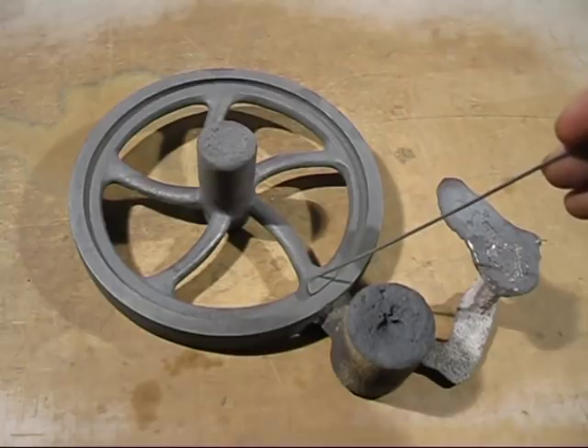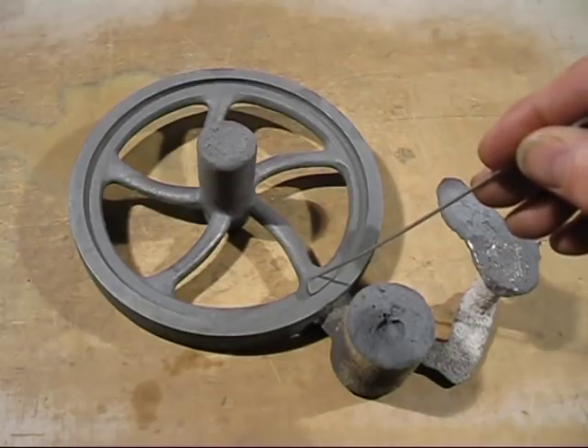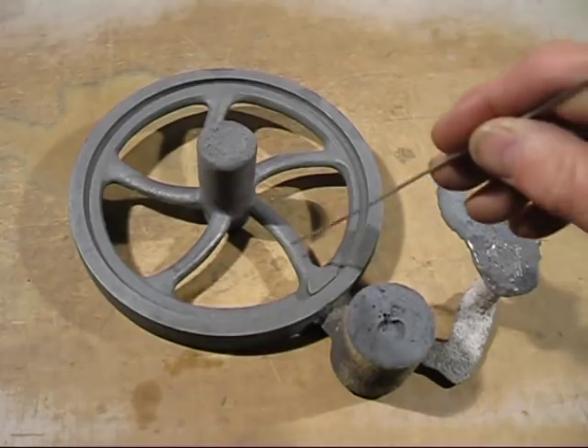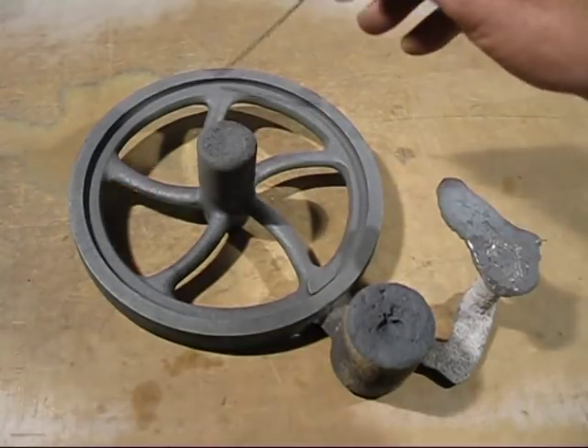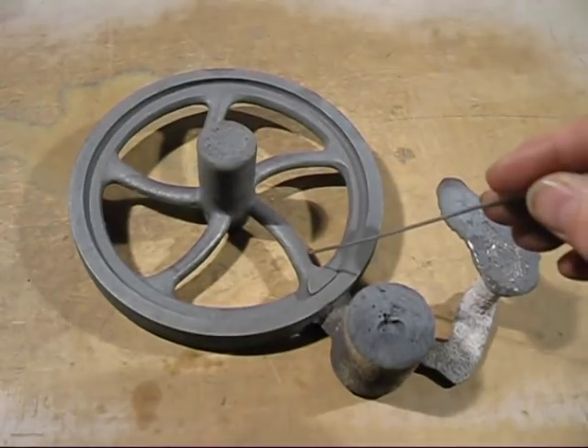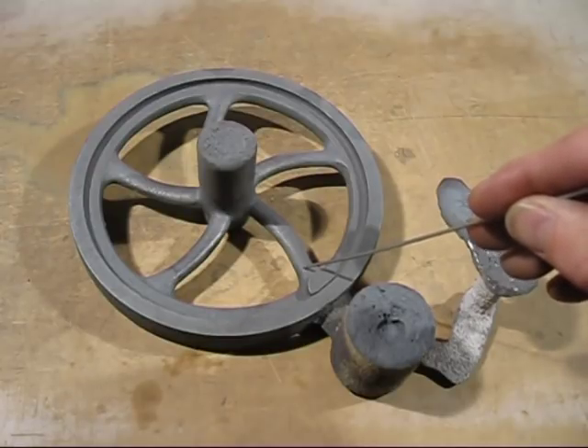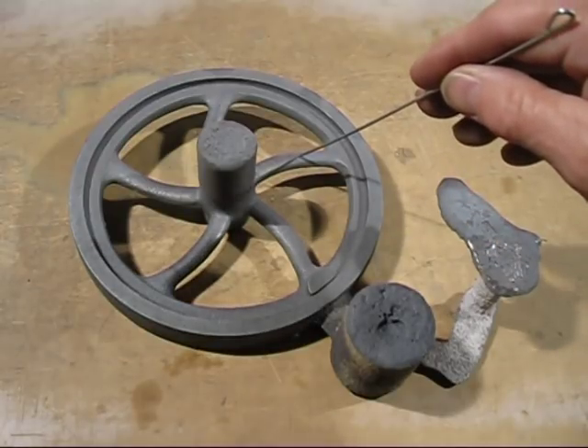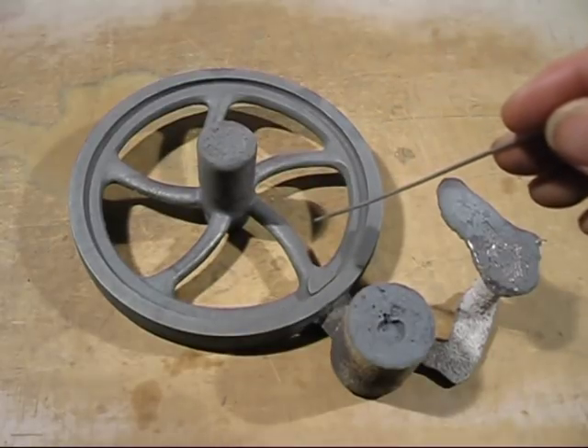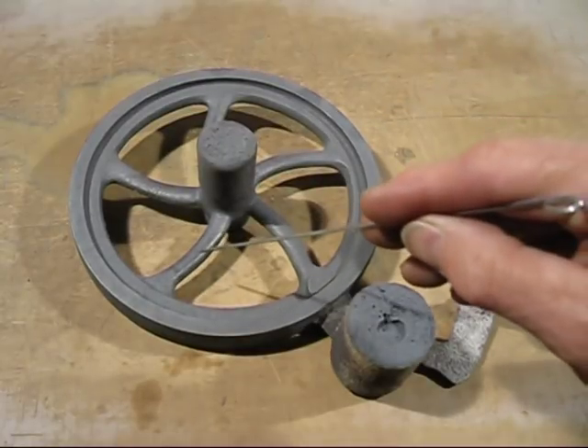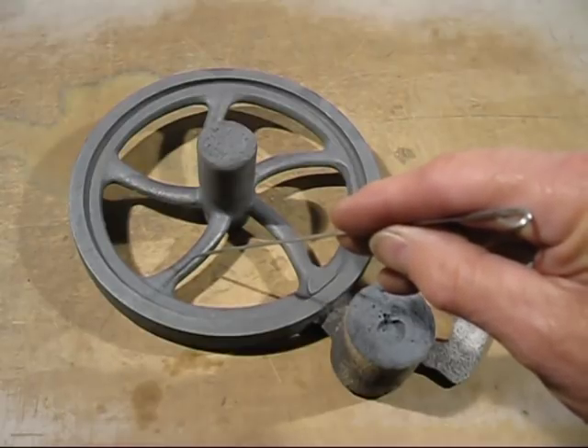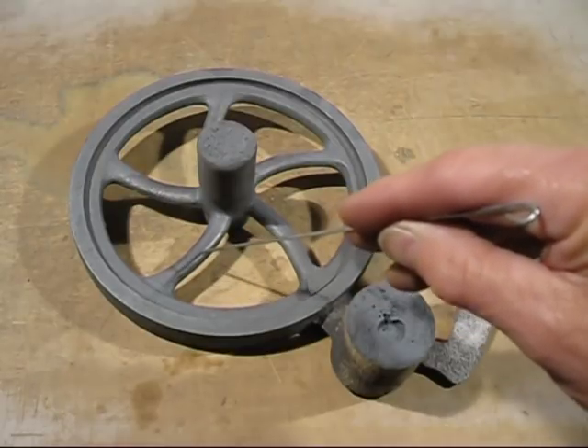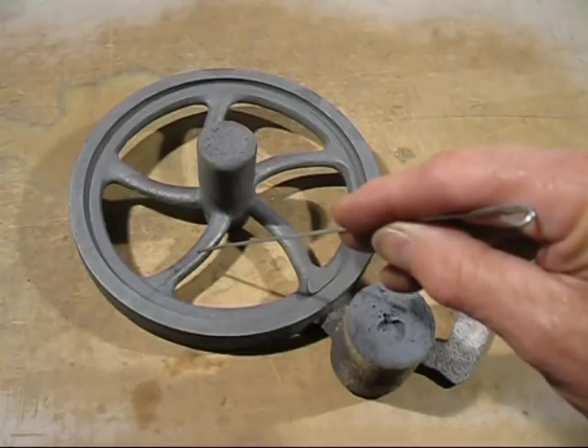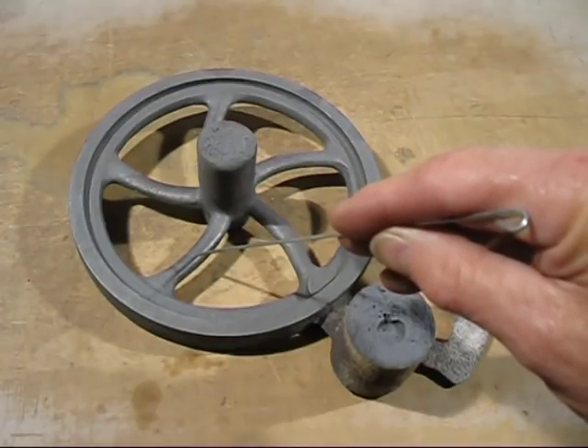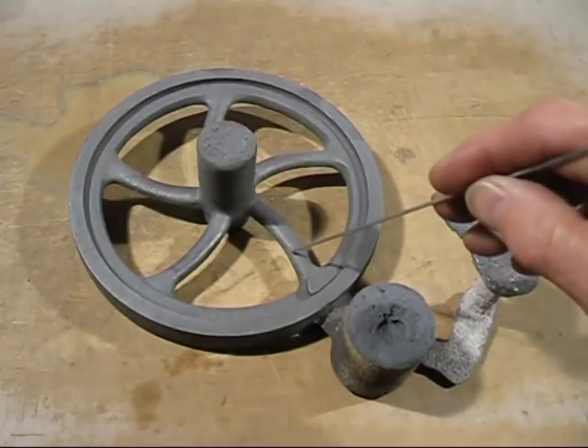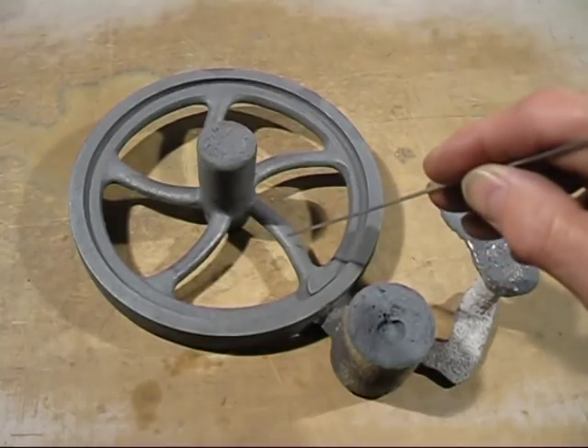And normally with these castings, I usually pour these first or second to make sure they fill up all the spokes and the rim. But as you can see, as I poured it last, it still filled up the mould. So that tells me my pouring temperature is correct. The one thing you may not see so well with the image is this spoke is fairly cool and smooth, and that tells me a warning sign. If I had poured this a little bit colder, it would not have filled up the mould.